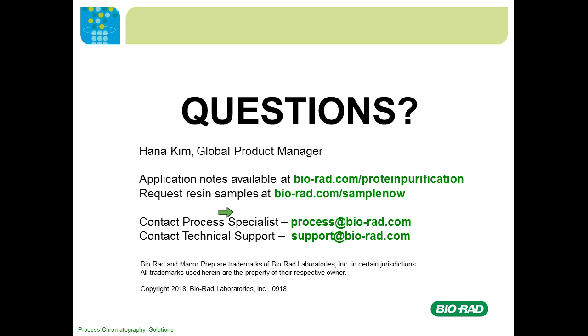Okay. And what will be the appropriate molecular size when using HPQ? If you consider your current process, the binding capacity is not high, and you believe it's due to the molecule, the pore size is too small, I would recommend you use Nuvia HPQ. And if you consider your recovery is low, maybe because your biomolecule was trapped and not able to recover from the resin, we also recommend you use HPQ.